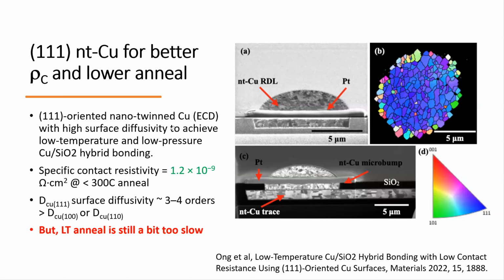But can you do it? Well, it turns out, yes, you can do it. A certain type of ECD chemistry will naturally give you a lot of 111. It's not 100%, not all 111, like 80%. That's pretty decent already. And using this method, published just last year, they found that their specific contact resistivity goes to E minus 9. This is crazily good, okay? It's pushing to the limit of copper bonding. And other types of material probably give you one order less.